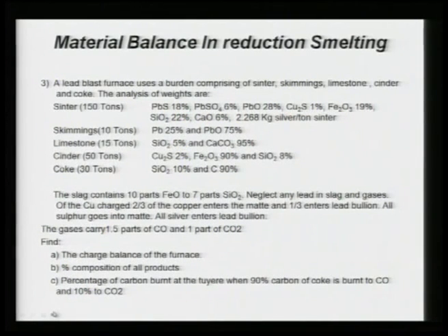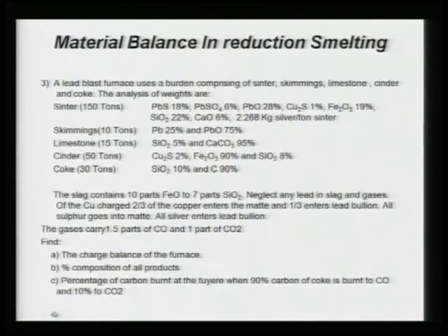So, you have to make a charge balance. With the term charge balance, you must be very clear what is being required here. You have to calculate the input and output both, that is what the balance means. Then the percentage composition of all products, and the percentage of carbon burnt at the tuyere, when 90% of the carbon of coke is burnt to CO and 10% to CO2. So, this point is to be kept in mind. Under that condition, you have to solve the problem.